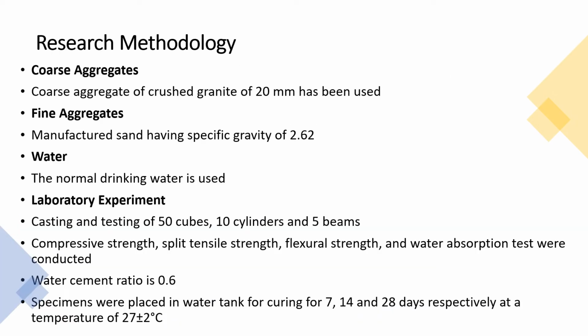Apart from using Portland cement and the waste paper ash, we have also used coarse aggregate, fine aggregate, and water, which are the normal ingredients for concrete. We have produced and tested 50 cubes of concrete, 10 cylinders, and 5 beams. The focus of our laboratory tests was on compressive strength, split tensile strength, flexural strength, and water absorption test. The water cement ratio to produce the samples was 0.6, and the samples were placed in a water tank for curing for the required number of days.